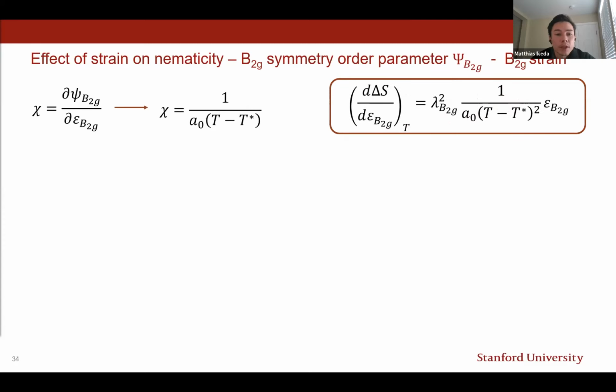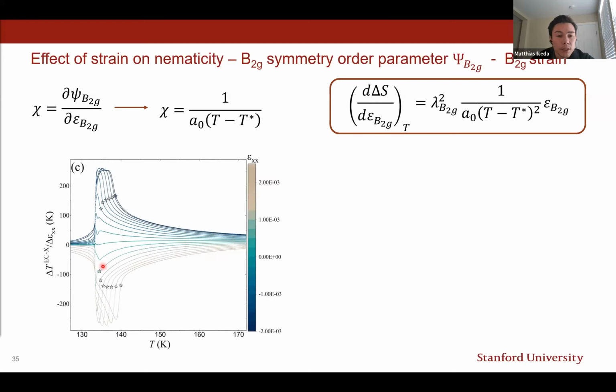As far as the temperature dependence is concerned, as long as the nematic susceptibility, and here we see it's the bare nematic susceptibility not renormalized by the lattice, follows Curie-Weiss temperature dependence, we expect the elastocaloric effect to follow 1 over (T minus T star) squared. And this is what we observe for parent barium iron arsenide.